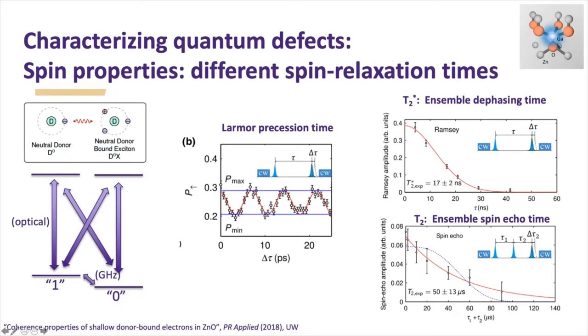In this particular case, it's the gallium donor in the crystal zinc oxide. So the energy level structure for the geometry that I'm working in this case is a little bit more complicated than the one that I saw. There's actually many, many interconnected couplings from that qubit level to optically excited levels. But the first thing that we can do is create a superposition state and then watch it precess in the magnetic field. And this is the Larmor precession that you see.